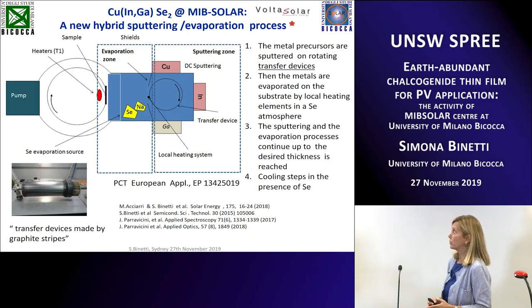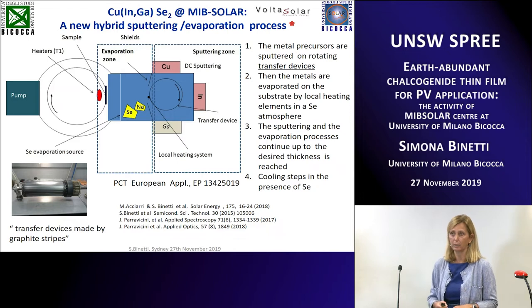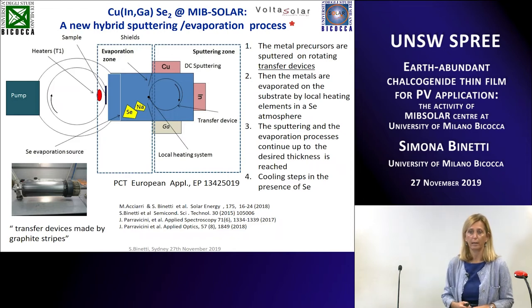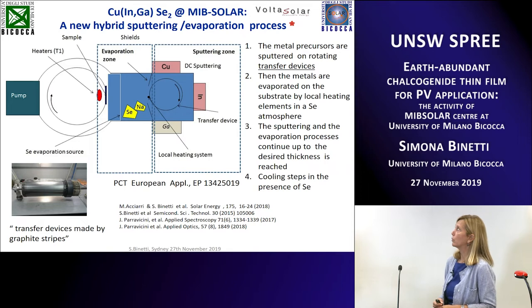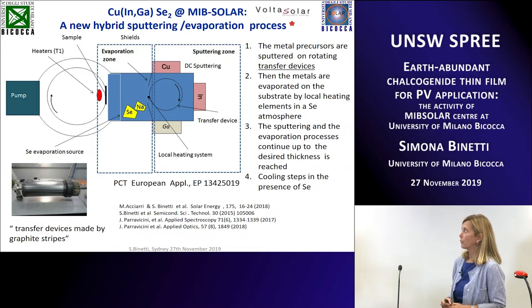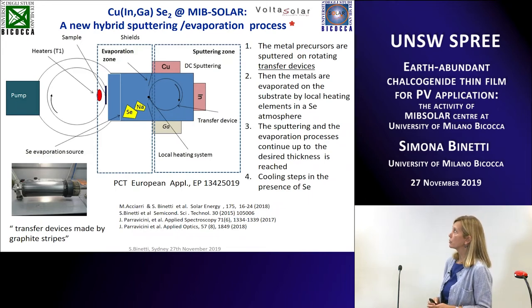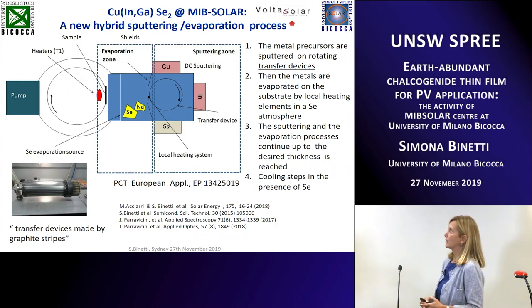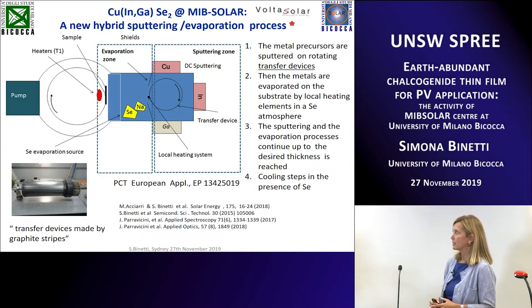One is the sputtering zone, and the other is the evaporation zone. In the sputtering zone, the metal precursors are sputtered not directly on the substrate, but on ad hoc devices that we call transfer devices, that is rotating one. Then, when these devices are in front of the substrate in the evaporation zone, there is evaporation of the metals by a local heating system in selenium atmosphere, because the transfer device is made of graphite stripes.